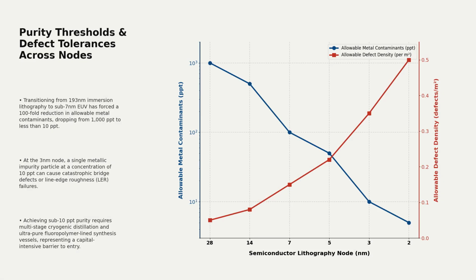The physical constraints of sub-7 nanometer lithography dictate these extreme market dynamics. As silicon features shrink, allowable metallic impurities have dropped 100-fold, from 1,000 parts per trillion down to 10 parts per trillion. At the 3 nanometer node, a single metallic particle at 10 parts per trillion causes catastrophic bridge defects. Achieving this level of purity requires specialized cryogenic distillation and fluoropolymer-lined vessels.